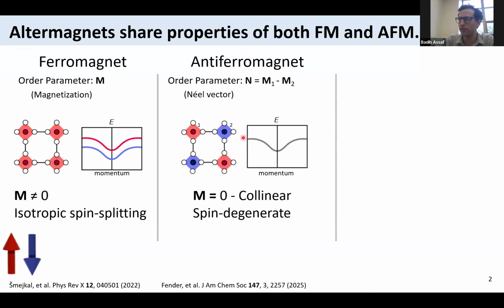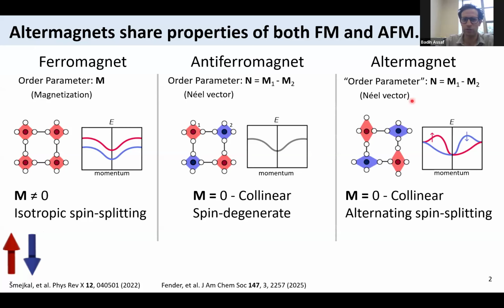It's not as simple as the antiferromagnet in momentum space, where in the antiferromagnet you just have essentially no spin splitting. It's a state where the Néel vector remains one of the order parameters. That's why I'm putting it in quotation marks. And I'm going to use it later on, but it's a state where the real space picture, the low symmetry of the crystal, allows and gives rise to spin splitting in momentum space. And this spin splitting causes a lot of the electrical and optical features that you normally see in a ferromagnet, despite the fact that these materials have zero and almost vanishing magnetization. And this is something that I'll show you experimentally in a bit.